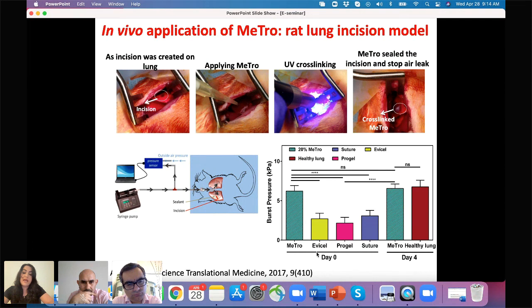And then here we show that based on the day 0 ex vivo data, Metro-sealed lung had higher burst pressure compared to conventional techniques that are used for sealing a lung. And also after 4 days, the burst pressure of the Metro-sealed lung approached healthy lung, confirming that Metro helped regeneration and repair on the defect side.